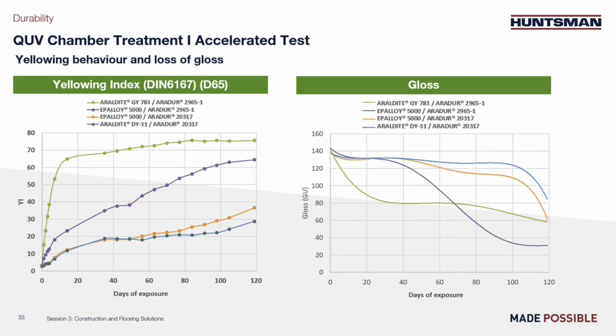On the left graph, you can see the yellowing index, and on the right graph, the gloss evolution versus time in QUV chamber. This QUV chamber is an accelerated test. And if we compare with results behind the window, they follow the same trend. Generally, we have seen that 15 days in QUV chamber is about equivalent to 1 year behind the window.